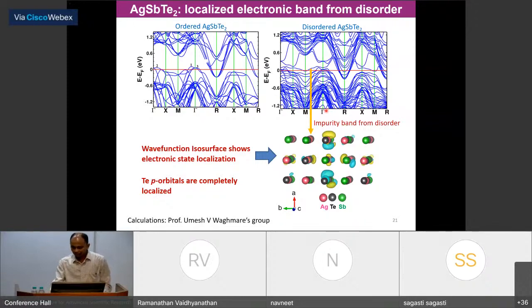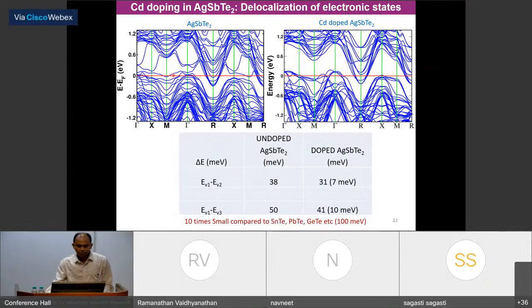So now let's see what happens if I dope cadmium. This is the disordered AgSbTe2, which has a localized flat band. This is a flat non-dispersive band which is actually the localized band. As soon as we dope cadmium, this localized band goes away. So that means the cadmium actually orders the silver and antimony, and it creates delocalization of electronic states, and also cadmium dopes extra holes in the system because cadmium is 2 plus, antimony is 3 plus. So it actually lowers the Fermi level. So basically cadmium is doing two things. It's delocalizing the electronic states. At the same time, it's moving the Fermi level away from the mobility edge. So we are working in a delocalized regime. That's what we want in thermoelectrics.